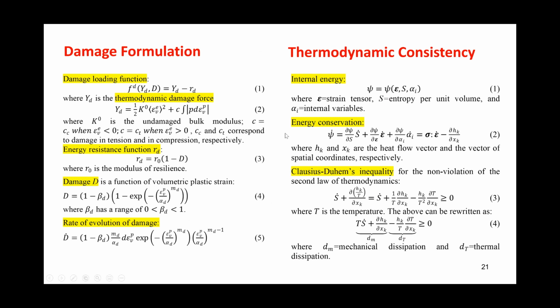Okay, damage. Damage consists of two competing components, a thermodynamic force Y sub D, which is a function of the volumetric strain. So now damage is a function of volumetric strain. In the first model, damage was a function of the axial strain. In the second model, damage was a function of the shear strain. Now the damage is a function of the volumetric strain.